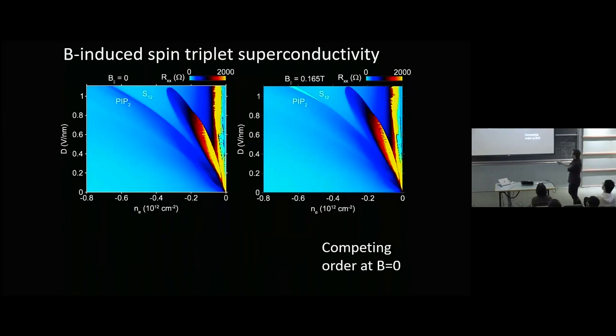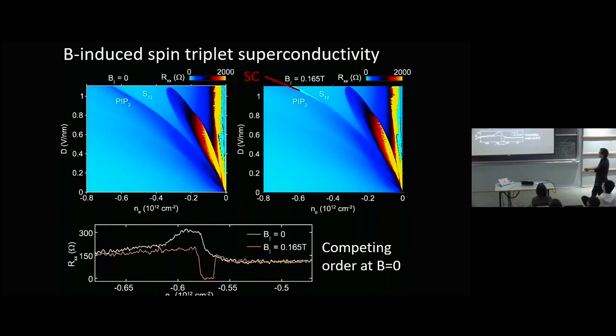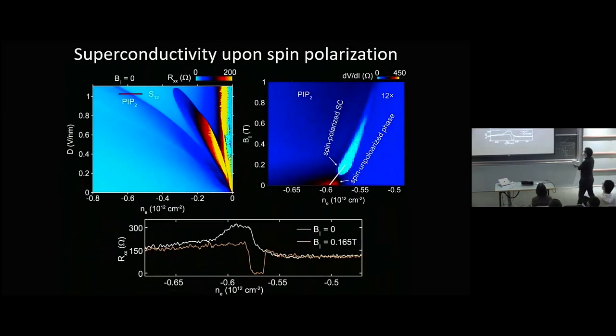So what I'm showing you here is transport data. These are all different ferromagnetic phase transitions that you see, changing the color scale here because there are sharp changes in resistance, but there is indeed no superconductivity at zero magnetic field. And in the process of understanding why that was the case, we made this surprising discovery that there's superconductivity only in applied magnetic fields. Okay? And in particular, only in rather strong applied in-plane magnetic fields. So you have no superconductivity at zero field, and then you apply an in-plane magnetic field, and you get superconductivity. Again, in between two phases, or maybe in a very narrow slice that corresponds to its own isospin polarized phase.